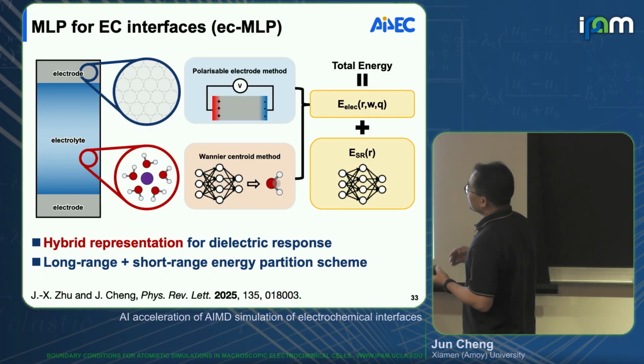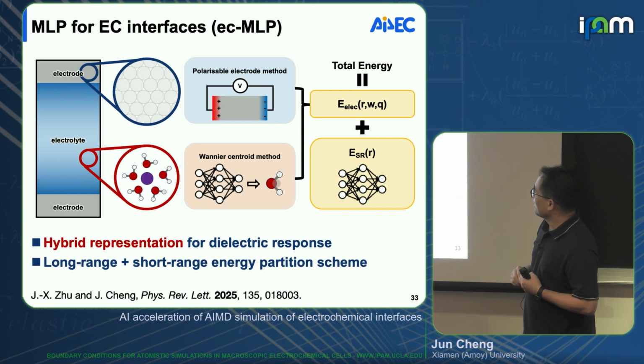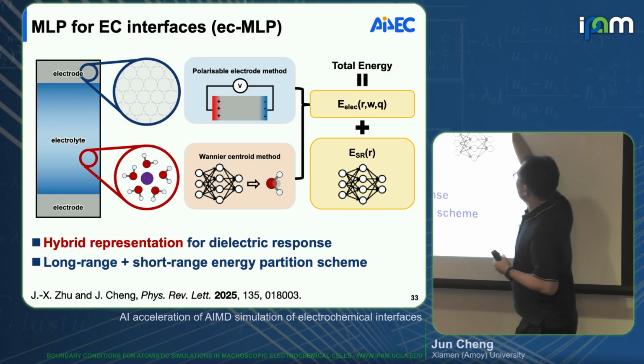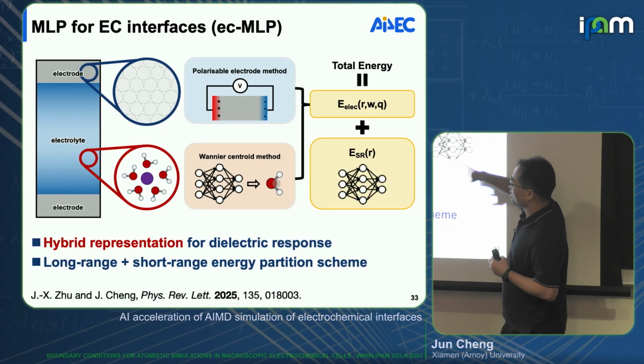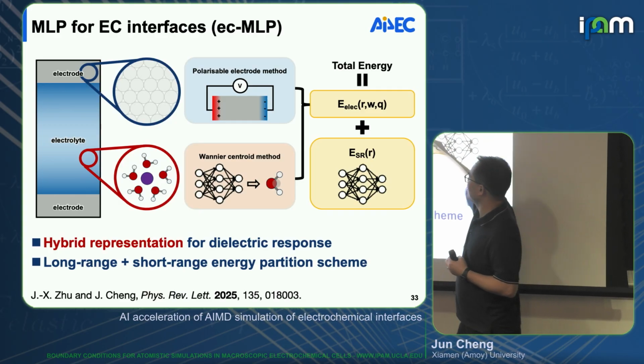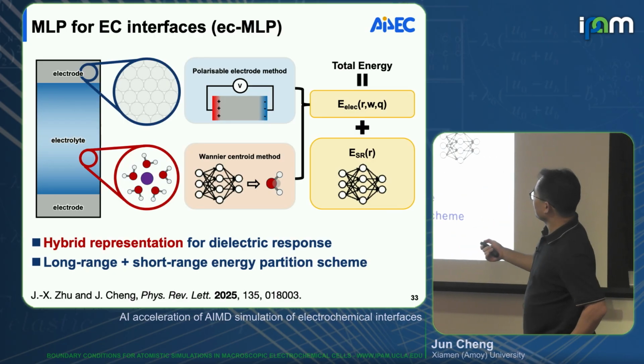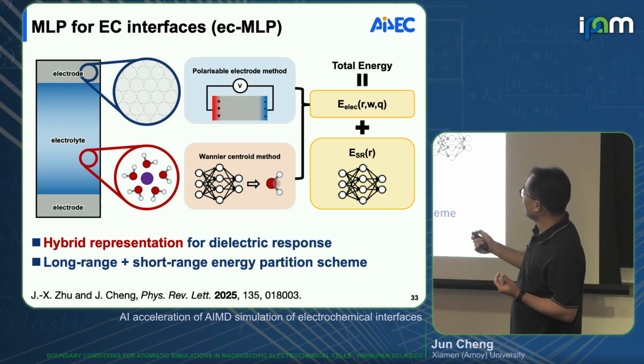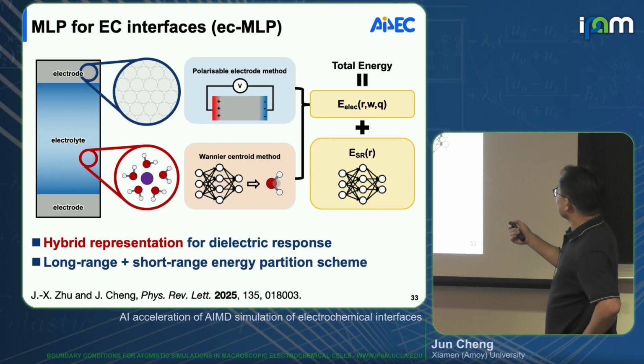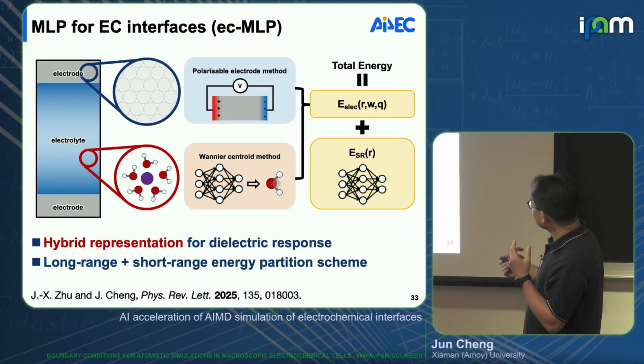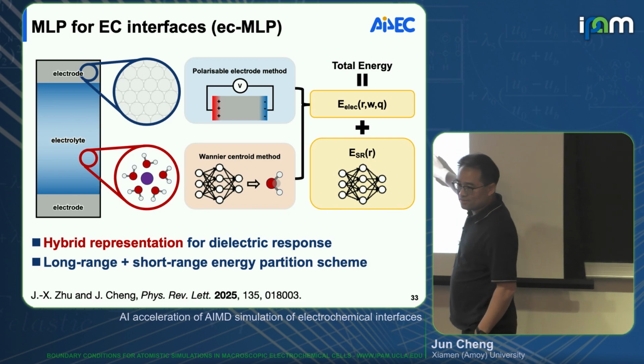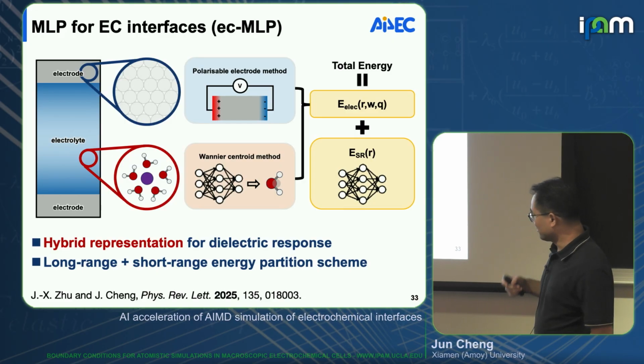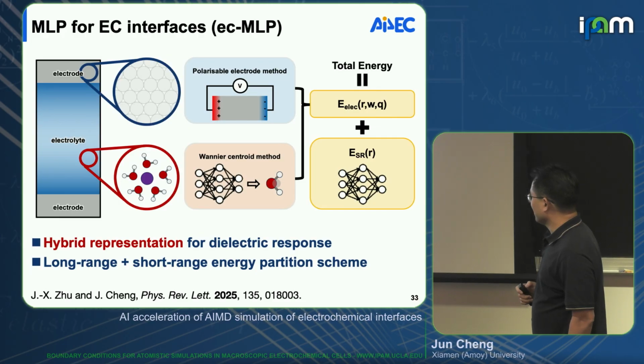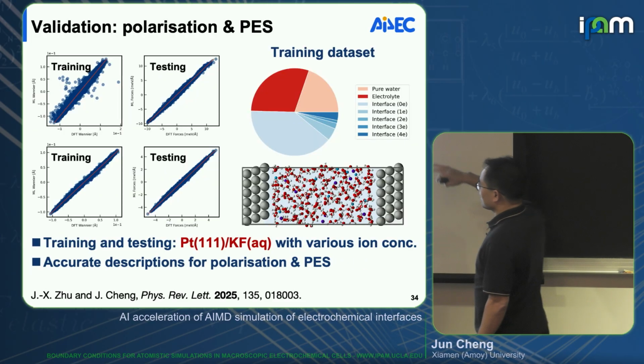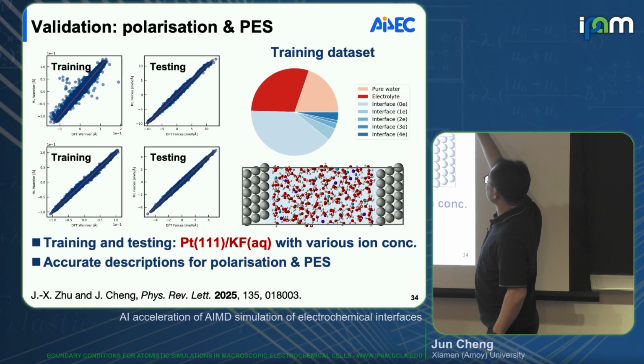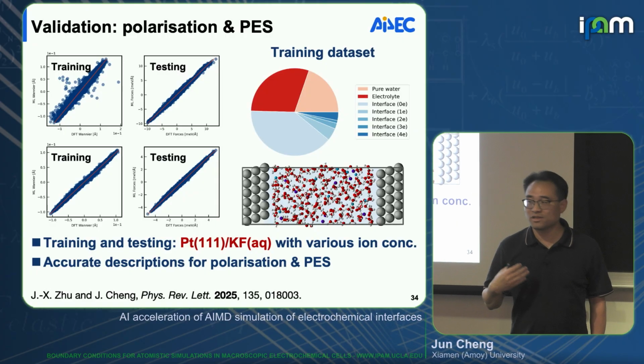So then the machine learning potential framework for this electrochemical interface is separated into two parts, like many people do in the field. For the long-range part, the long-range electrostatics, we explicitly treat the polarization by combining the Wannier centroid for the electrolyte and the polarizable electrode for the metals. And taking out those electrostatics, the residual energy, the short-range part, is learned using the standard DP framework. So now we have a hybrid representation for the metal-water interface. That's the training set we have, including pure water, electrolyte, and also interfaces with various surface charge densities.